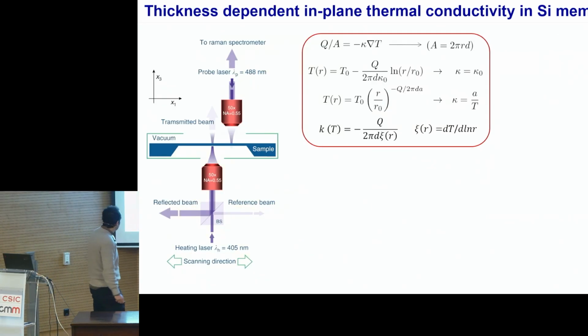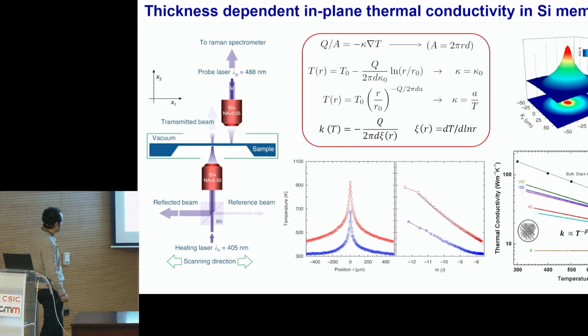So we measure this with the 2 laser Raman thermometry. I will not say a lot of details about this technique, which is very well established. 2 lasers, 1 laser to have the thermal excitation to create the spatially dependent thermal field, and 1 is the temperature sensor. And by using this model, actually we can extract the thermal conductivity by measuring the absorbed power, the thickness of the membrane, and this factor which we get from the experimental data, which is this slope.